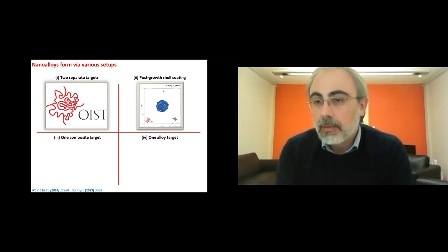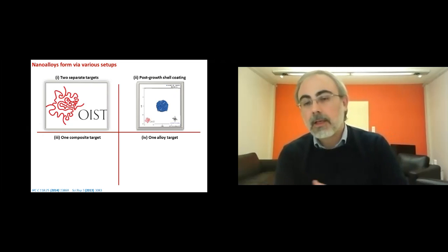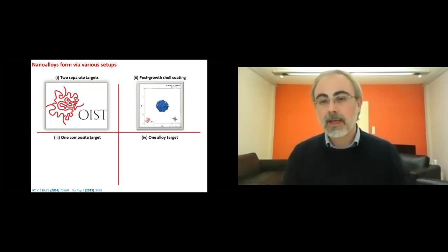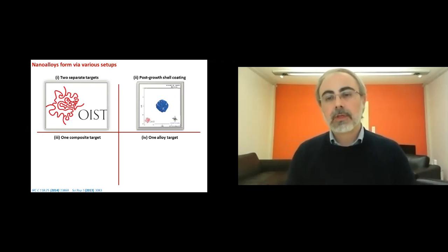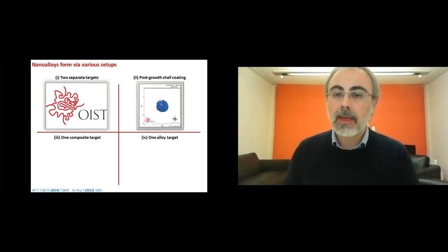When we try to grow purely silicon clusters, we found that the probability of having crystalline clusters is much lower when you go down with the size. So the probability increases when the size increases. But using silver inoculation for these clusters, you end up with a crystalline structure.